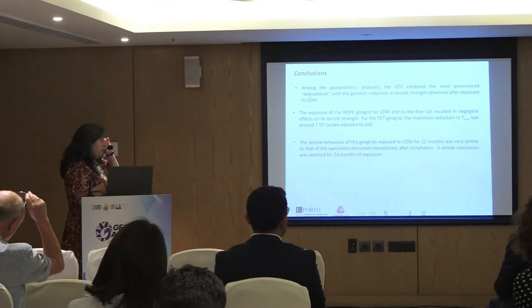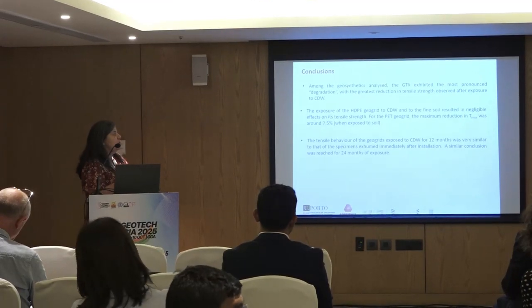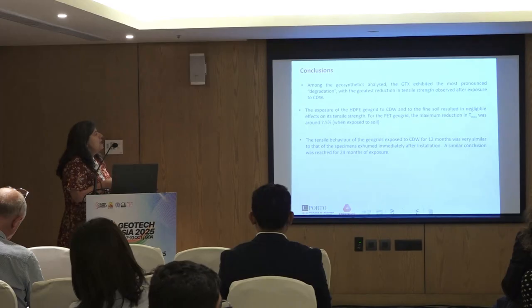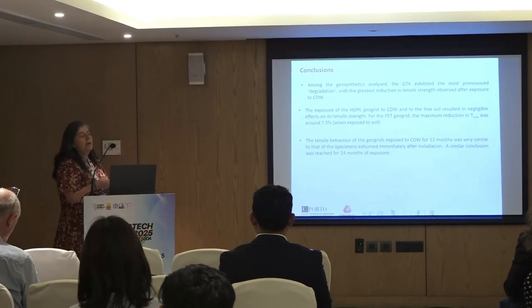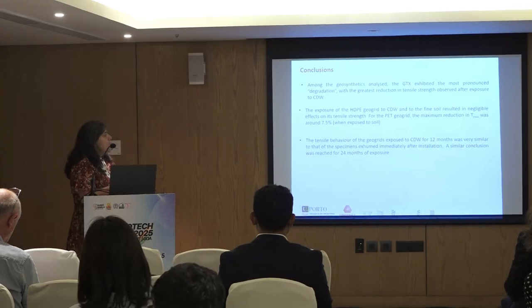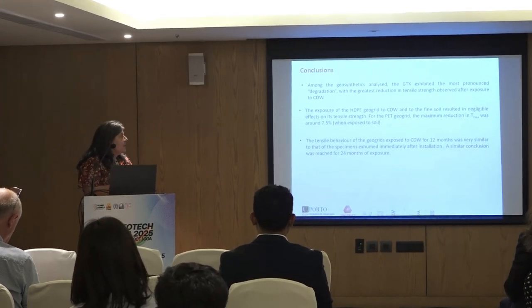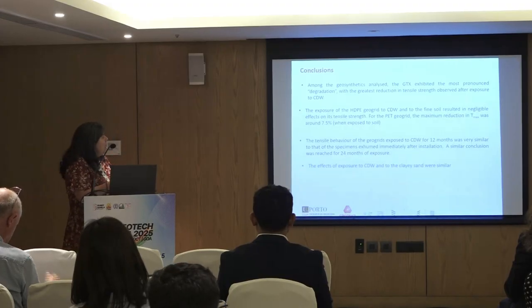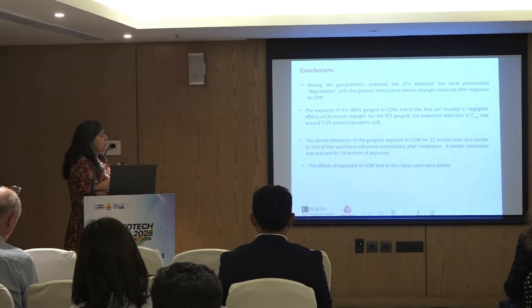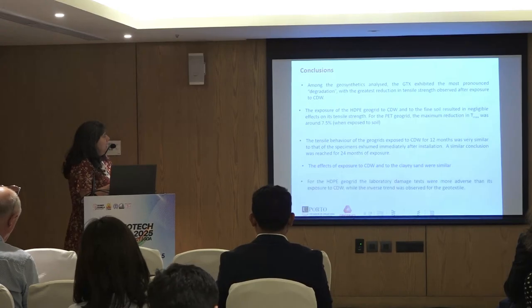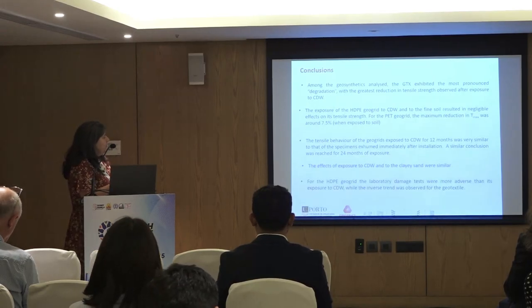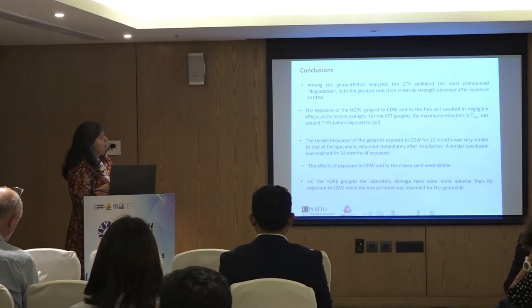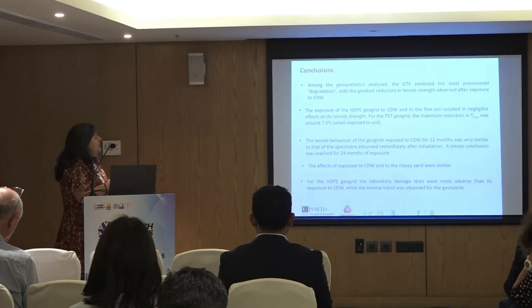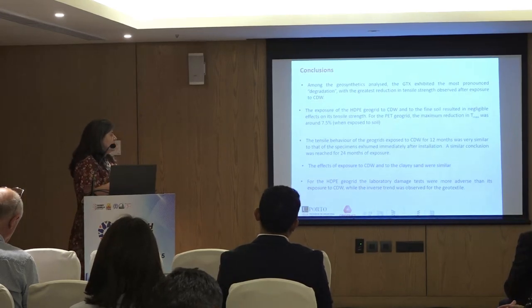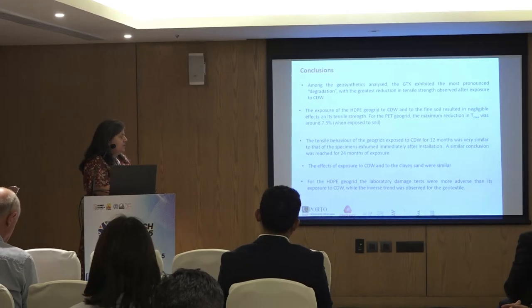The tensile behavior of the geogrids exposed to the recycled materials for 12 months was very similar to that of the specimens exhumed immediately after installation. A similar behavior was observed for the geotextile, where the results for exposure to the recycled material and to the clayey sand or the fine soil were quite similar. And to conclude, for the HDPE geogrid, the laboratory damage tests were more adverse than its exposure to construction and demolition waste, while the inverse trend was observed for the geotextile.